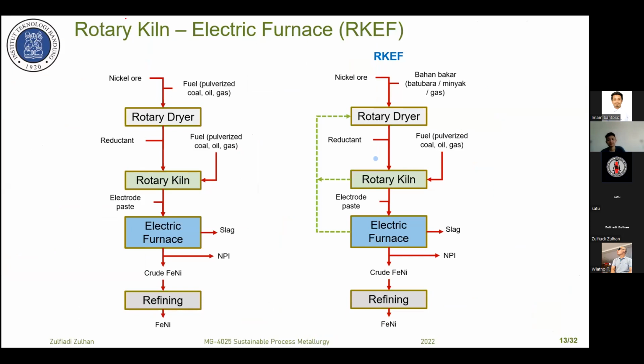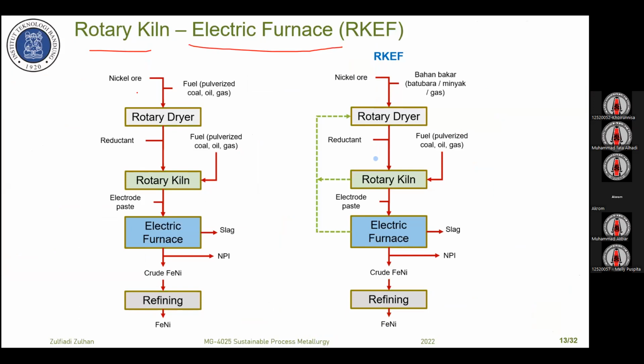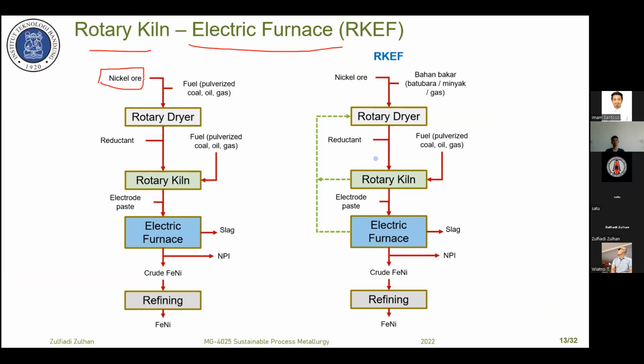Now we focus on the rotary kiln electric furnace technology. If we look at the routes, there are two kinds of route. On the left-hand route, the nickel ore is sent to the rotary dryer for removal of surface water, around 30 to 40% of moisture is removed. The product from the dryer has a moisture content of around 20%.